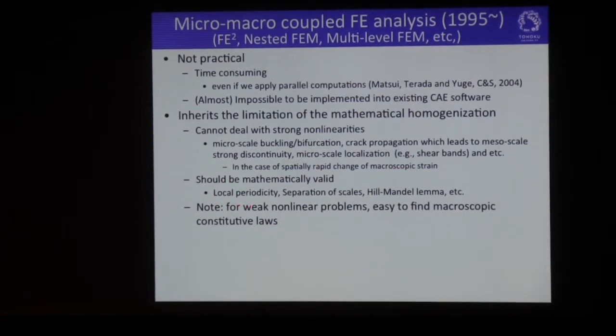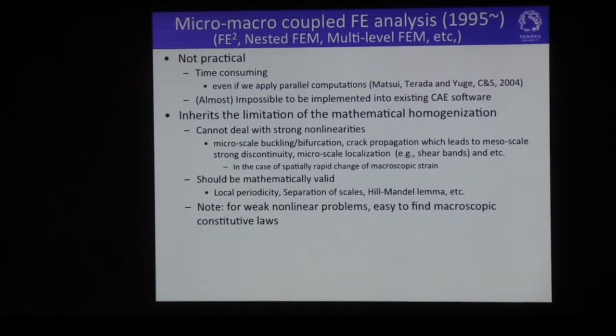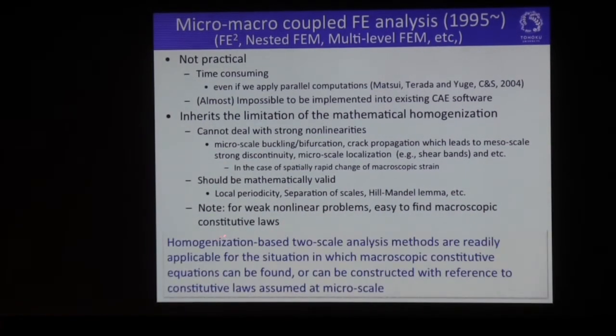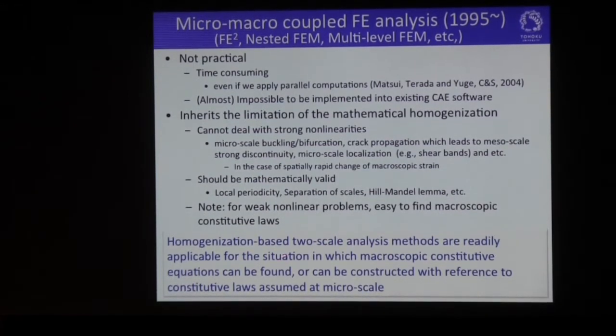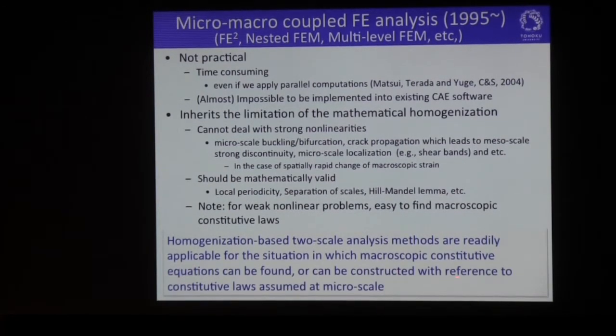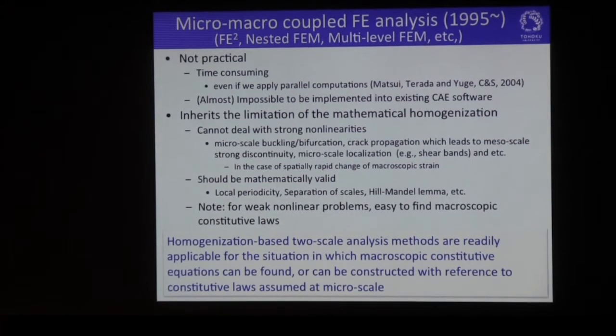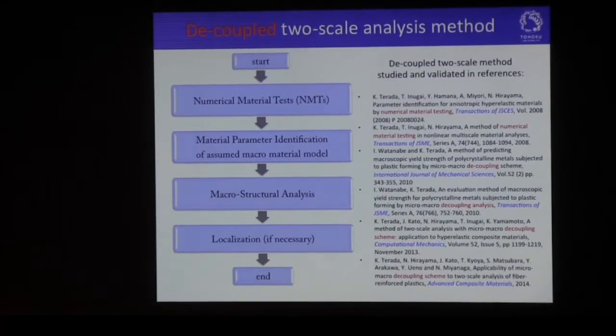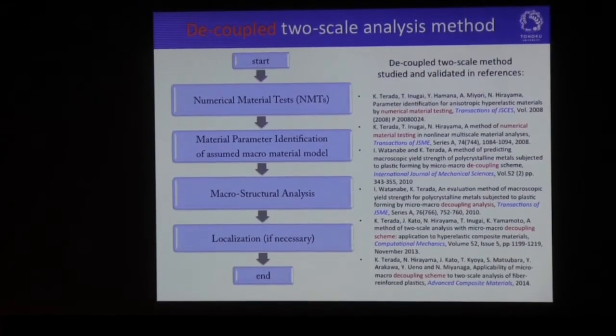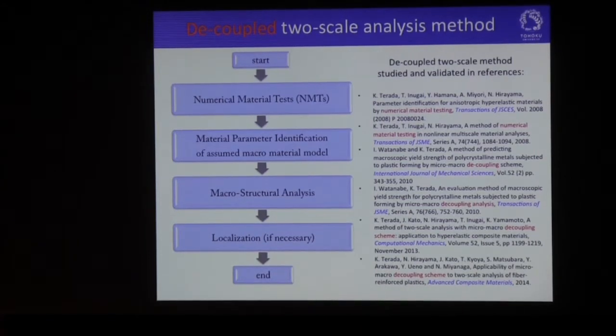So we note that for weak nonlinear problems, it's very easy to find macroscopic constitutive laws. So my assertion is that the homogenization-based two-scale analysis methods are readily applicable for the situation in which the macroscopic constitutive equation can be found or can be constructed with reference to the constitutive laws assumed at the microscale. This way, I gave up this coupled method 10 years ago, although I was the one who originated the coupled method.